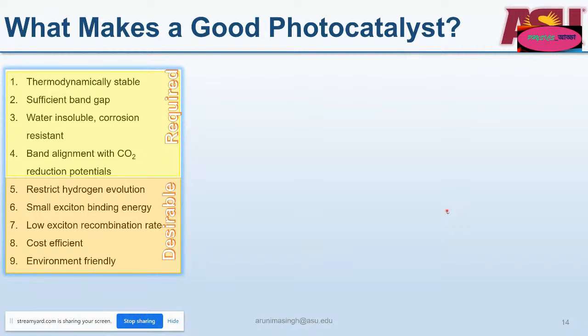The desirable properties include that the competing reaction of hydrogen evolution should be suppressed. Your protons should actually react with CO2 or its intermediates instead of reacting with themselves and forming hydrogen. These materials should have small exciton binding energies so that you have lower overpotentials. And they should have low exciton recombination rate so that you don't lose energy because of this recombination. It should be, of course, cost efficient, environmentally friendly. So I have a huge list of what I want.